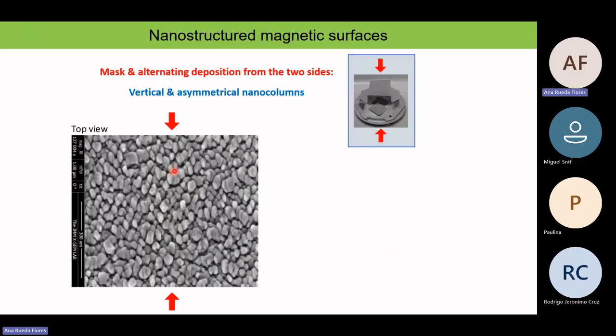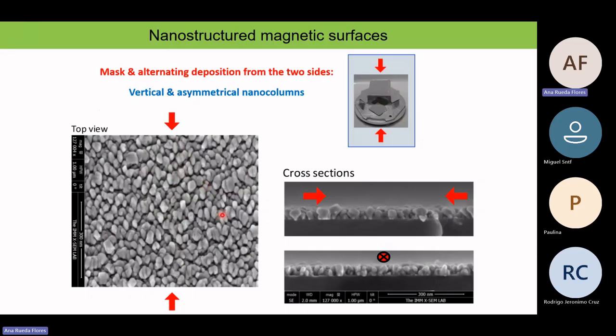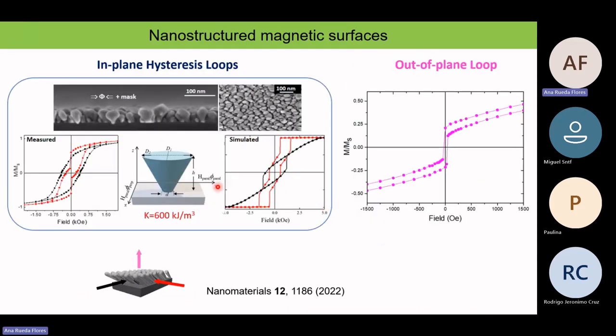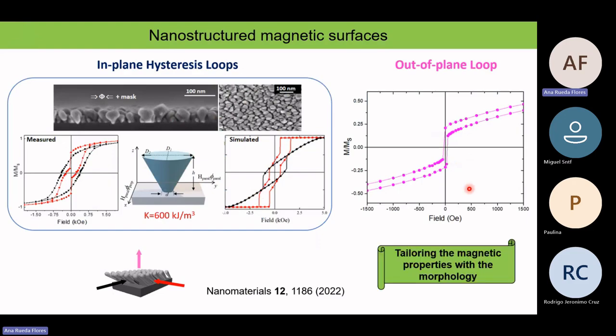So this is a top view image. You can see that this is asymmetric and it's vertical. So in fact, the shape is like an inverted truncated cone. And you can see here the experimental loops. So we have an asymmetry in the plane, so we have different loops in the plane. And as we have a vertical shape, we have a certain squareness in the perpendicular loop. So the take-home message is that we can tailor the magnetic properties with the morphology.